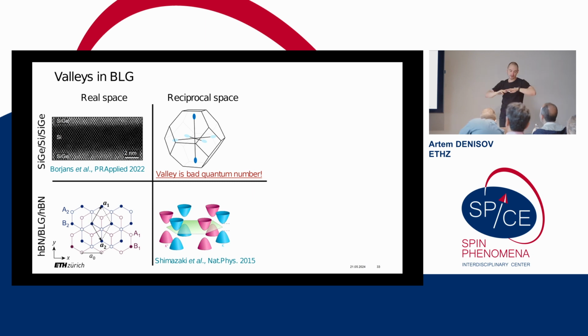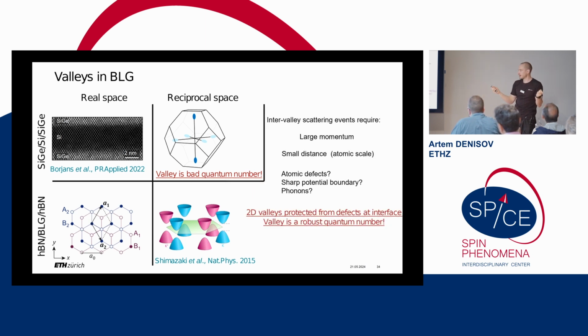But what about graphene? In graphene, everything is 2D, so your Brillouin zone is also 2D, and your valleys are separated in the X and Y plane. They are also separated very far from each other, the distance being a reciprocal lattice vector, which is 1 over your lattice constant. It's a huge momentum. The only scattering mechanism which can lead to such a momentum swing, to scattering from one valley to another, is really an atomic defect. And as we know, devices made by dry transfer and encapsulated are very flat. There are no sharp interfaces and no real atomic defects. It means that 2D valleys are really protected from the interface disorder, the main source of relaxation in silicon, meaning that the valley is a really good quantum number in graphene. So why don't we use it to make a qubit rather than spin?